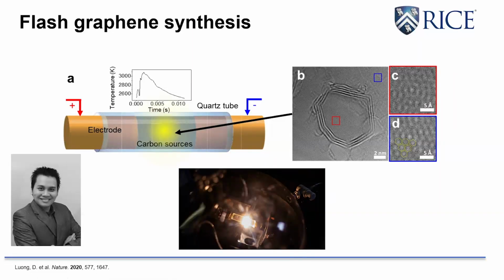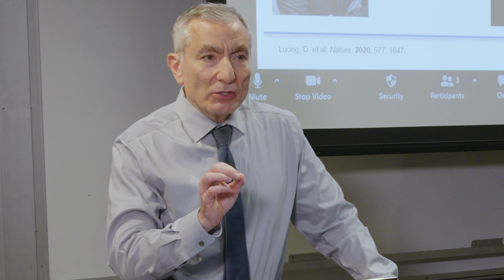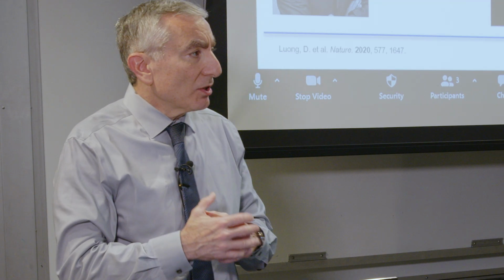And he put in enough energy such that there was so much energy in this that every carbon-carbon bond breaks. What he used was carbon black. So every carbon-carbon bond breaks. The non-carbon elements sublime out. They could sublime out the sides here. They go out the sides here because these electrodes are not tightly fitted in here. And so then what will happen is every carbon-carbon bond breaks, and then it reassembles upon cooling. It reassembles to the thermodynamically most stable arrangement of carbon atoms. And that's graphene. And so you get graphene, just like that.